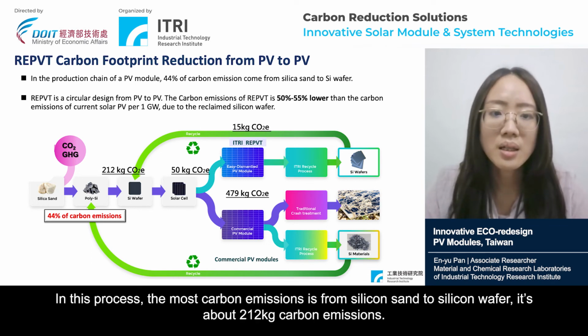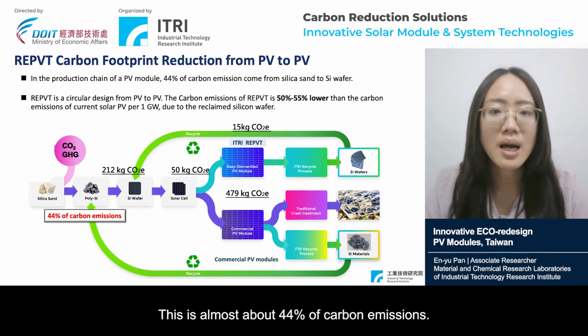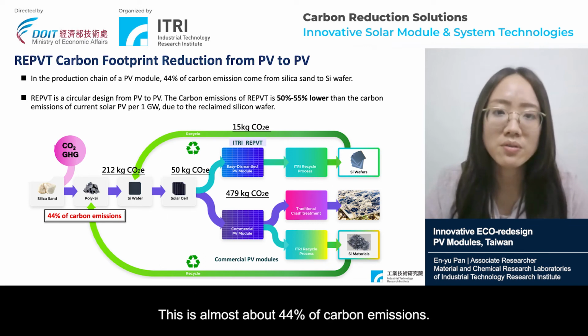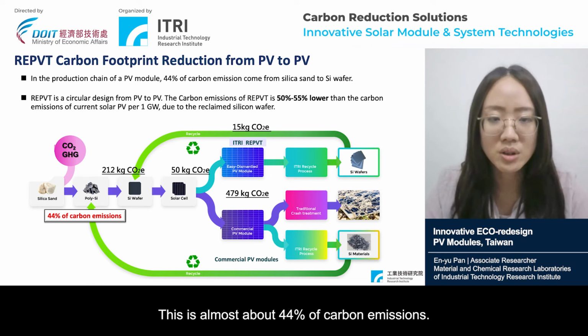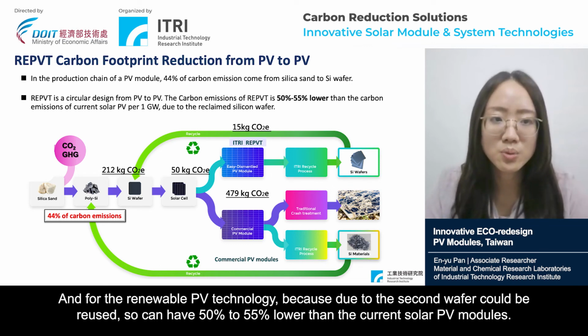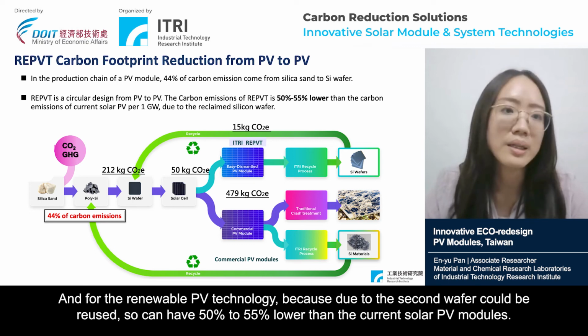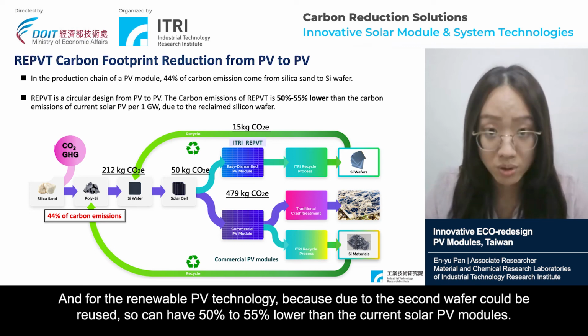And in this process, the largest carbon emission part is from silicon sand to silicon wafer. It's about 212 kilograms of carbon emissions. Yeah, this is almost 44% of the carbon emissions. And for the renewable PV technologies, because the silicon wafer can be reused, we can have 50% to 55% lower emissions than the current solar PV modules.